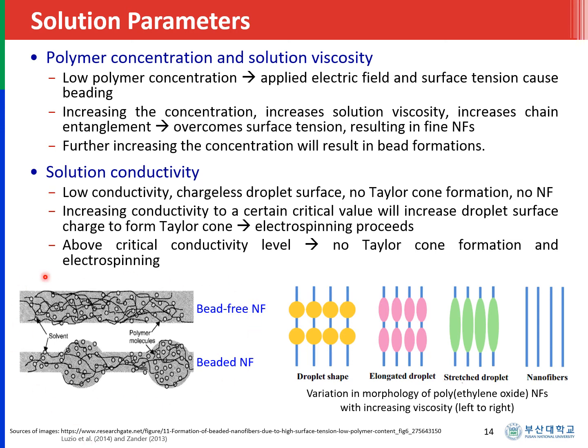This figure shows images or an illustration of bead-free and beaded nanofibers. And in that nanofiber, you would see the interaction between the solvent molecules and polymer molecules. This illustration shows the variation in morphology of polyethylene oxide nanofibers with increasing viscosity. So as the viscosity increases from left to right, the morphology of the nanofiber becomes better. So the rightmost image shows the best or the high performance nanofibers, while the first three from the left are beaded nanofibers.